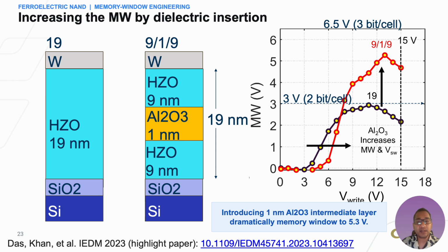This moves us from a memory window consistent with roughly 2 bit per cell operation toward a 6.5 volt target that we associated with 3 bit per cell NAND operation. The aluminum oxide layer is not a ferroelectric. It changes how the applied voltage divides across the stack and how the two HZO regions switch. The result is greater threshold leverage without exceeding the geometric budget of 19 nanometers.